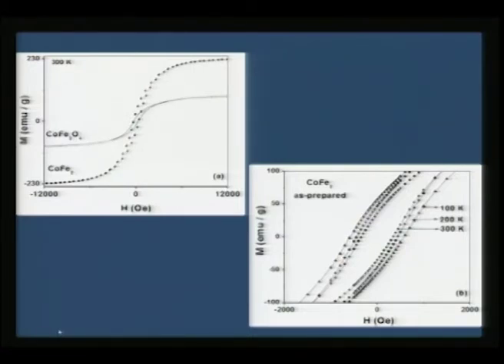If you take a typical M versus H loop, the alloy composition will have more moment compared to the oxide composition. So you clearly see the change in the magnetization values between the alloy and the compound, and as you see here, the change in the coercivity is also there. For the alloy as-prepared powder, if you do a temperature sweep, it says that this is truly a ferromagnetic alloy.